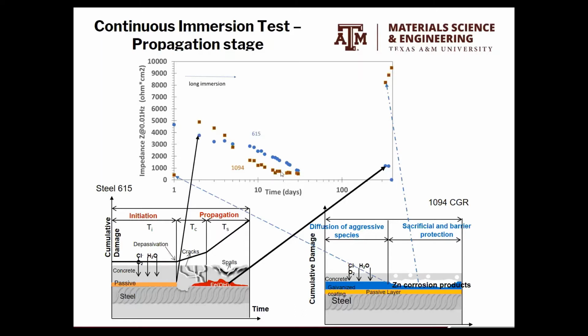And you see that there is a plateau, and then there is a point where the corrosion resistance increases. Why? Because we are forming a very nice, uniform, and this is the hypothesis, and we need to elaborate more on this hypothesis later, we are building a very nice corrosion products layer with time. That's why we have corrosion resistance for the zinc layer higher than the corrosion products from the steel.